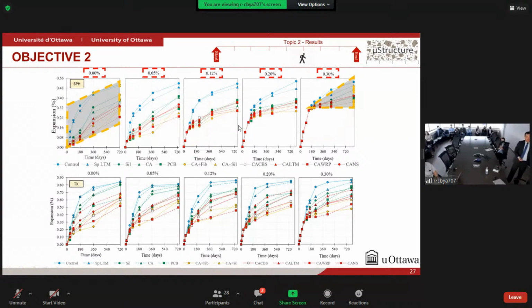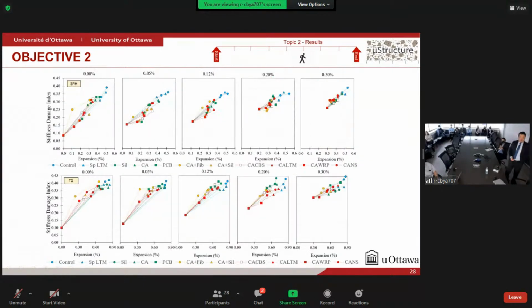Evaluating the internal damage of the concrete. First, I would like to highlight again that all mixture surface treatments were able to change ASR expansion development, but once they reach specific expansion amplitudes, we can see that the internal damage for comparable expansion is pretty much the same among the different surface treatments. The only exception here is the combination of CA with fibers that shows lower expansion development, but higher internal damage.